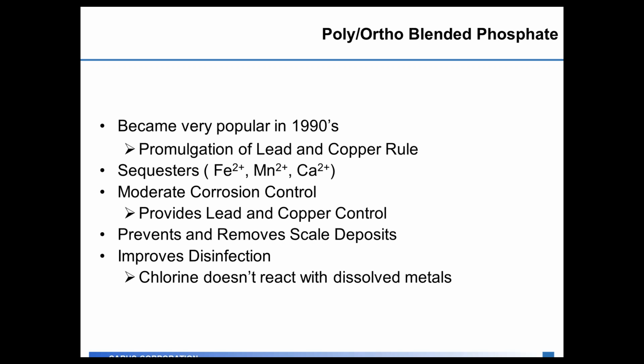What they do is they provide moderate corrosion control, so some lead and copper control to the distribution system. They help you prevent and remove scale deposits of iron, manganese, and calcium carbonate in the distribution system. And because they impact the biofilms, they can help improve disinfection, because as you remove that biofilm from the distribution system, you don't need to feed as large a chlorine dosage to maintain the same chlorine residual throughout the distribution system. So the idea here is feeding one blended product to get you all these benefits to the drinking water.